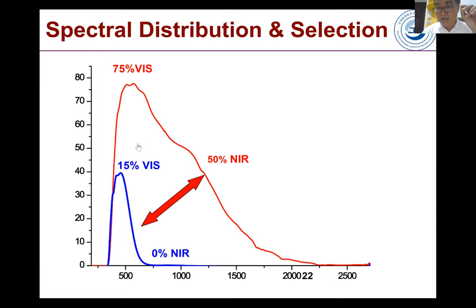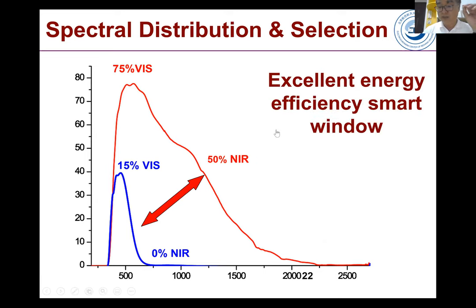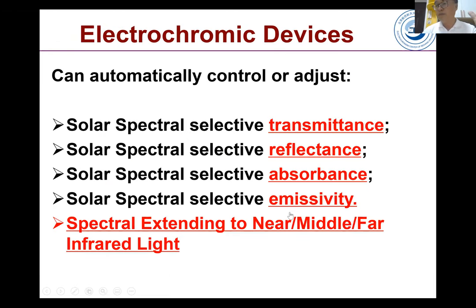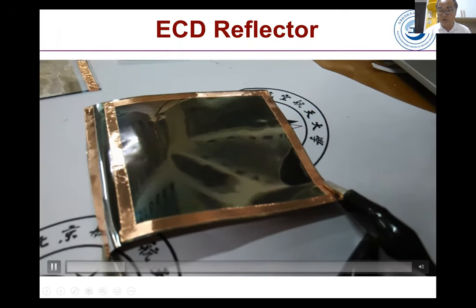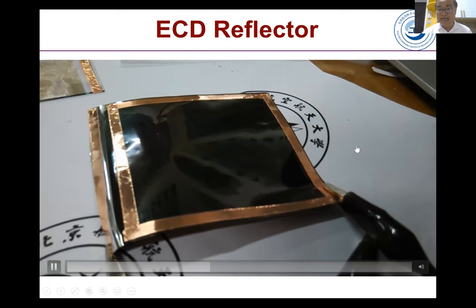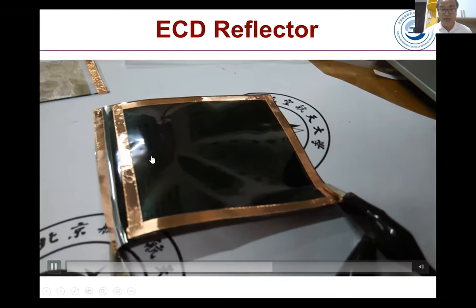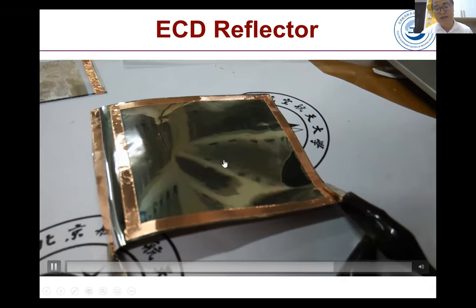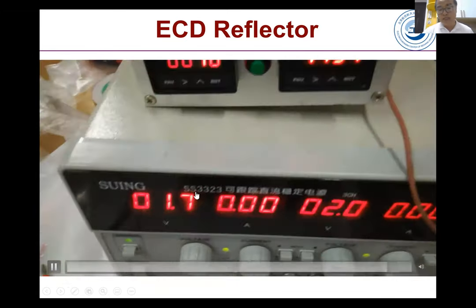Electrochromic devices can adjust not only transmittance, but can also be applied to solar spectroselective transmittance, reflectance, absorptance, emissivity, and so on. Therefore it is a very good device or technology to smartly control those kinds of electromagnetic wave properties. We have also developed this for satellite surface control. Using a flexible PI substrate, we make layer by layer coatings, and you can see this color changing. Using a cell phone maybe. And the voltage is very small, only 1.7 volts to drive such devices.